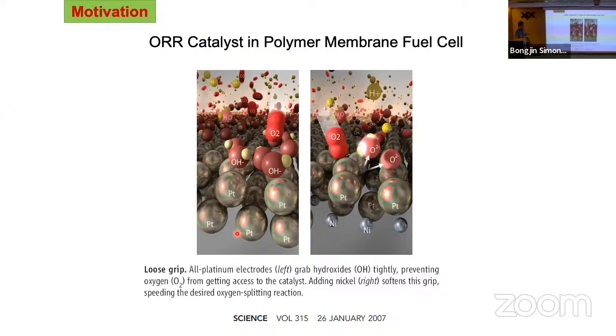So around 2007, there were a series of papers that came out from Berkeley and Oak Ridge National Lab. And the idea was, if they could somehow replace some of the platinum with nickel, then the normal reactions of the platinum, by replacing with this nickel underneath, they change the characteristics of the platinum, like tuning the electron structures, and then it can function somehow much easier. And this is the whole idea at the time.